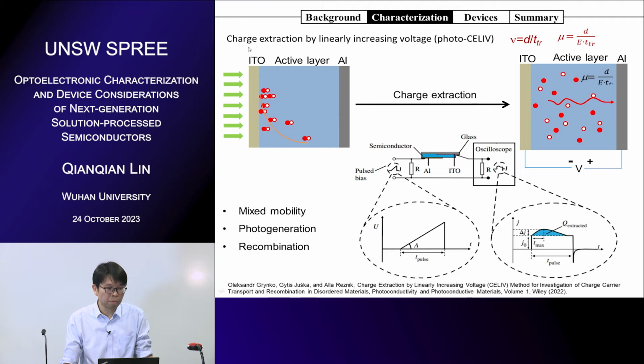So this is another method called charge extraction by linearly increasing voltage, or shortly we can call it photo-CELIV. For photo-CELIV, we also use a laser pulse to excite the semiconductor, and we can get charge generation, but we extract the carriers not immediately with a constant bias. We constantly increase the bias voltage linearly. Then we can get a displacement current like a rectangle here. Then we get extra carriers just from the photoexcitation. So the blue area here comes from the photoexcitation, and underneath is the displacement current.